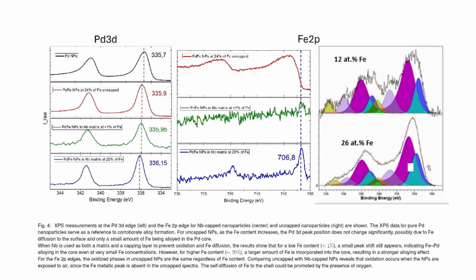The iron 2p spectra show that in uncapped nanoparticles, oxidized iron phases appear regardless of the iron content and the metallic iron peak is absent. This tells us that oxidation happens when the nanoparticles are exposed to air, and probably that diffusion to the surface is promoted by the presence of oxygen.